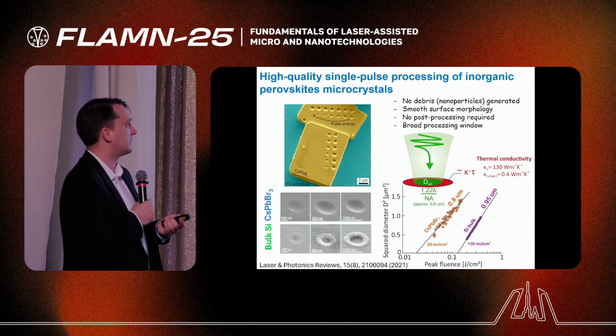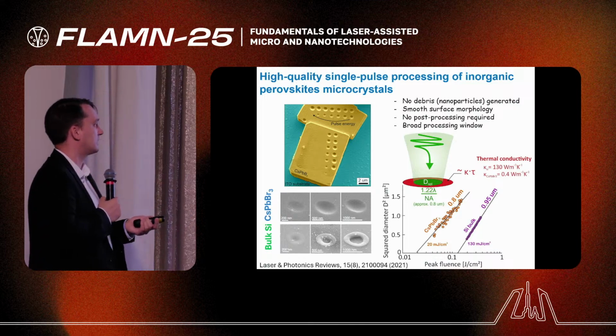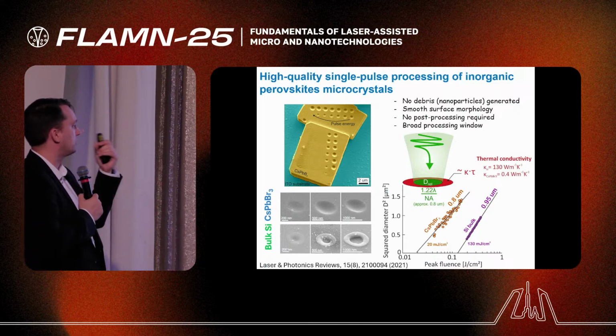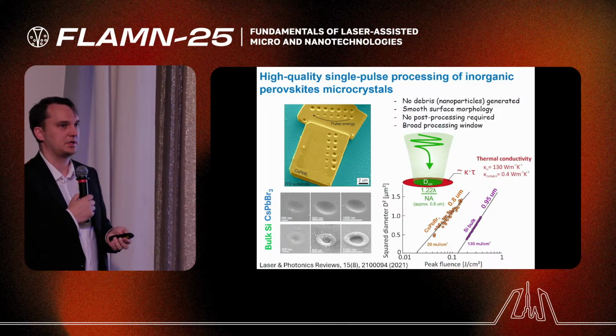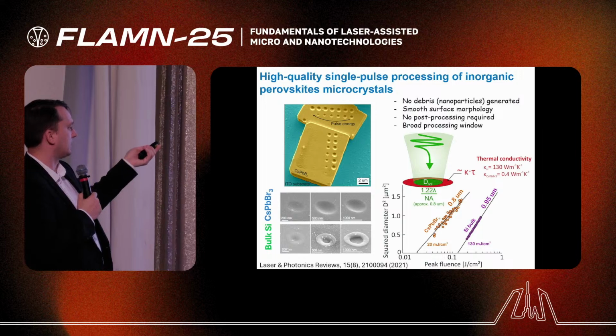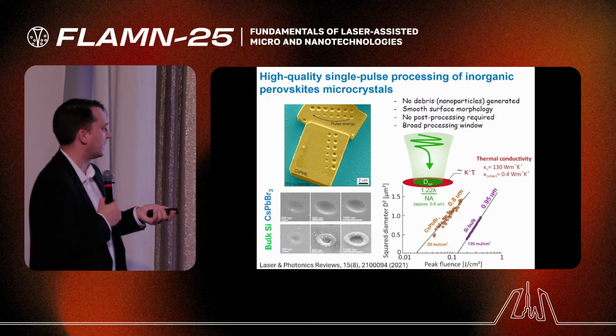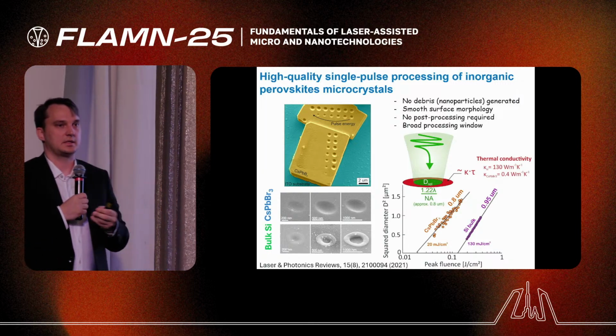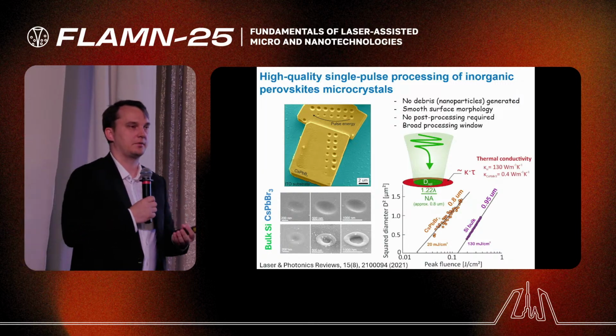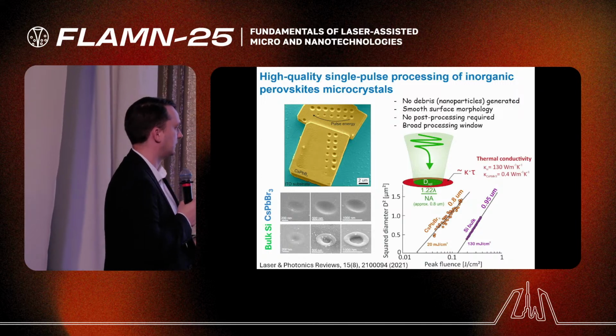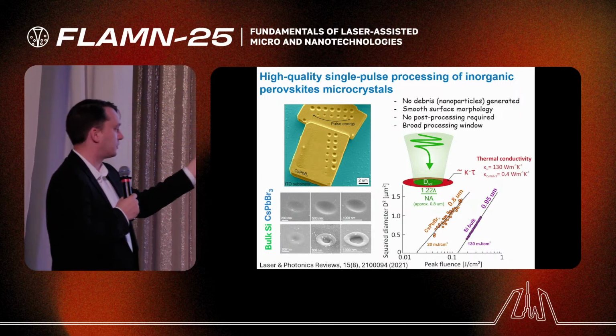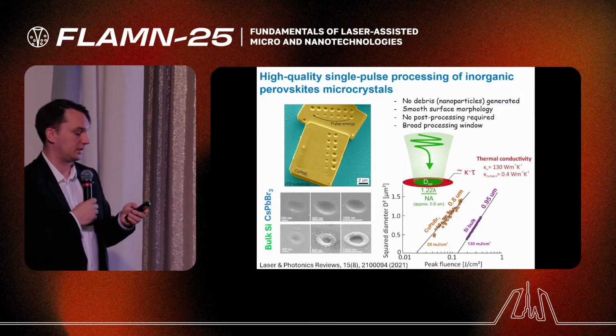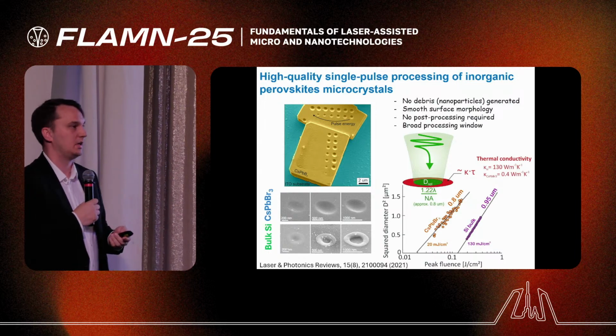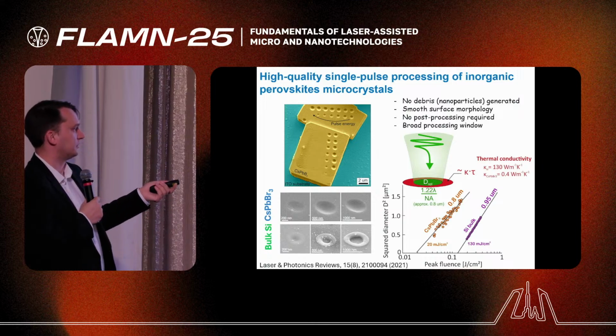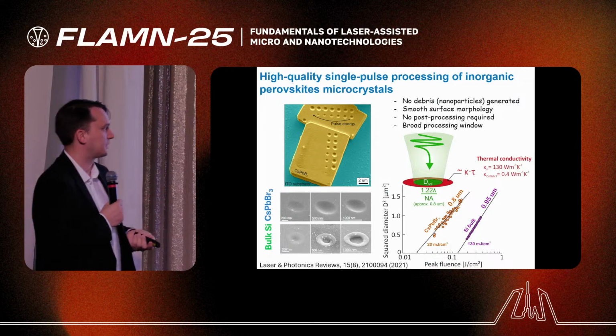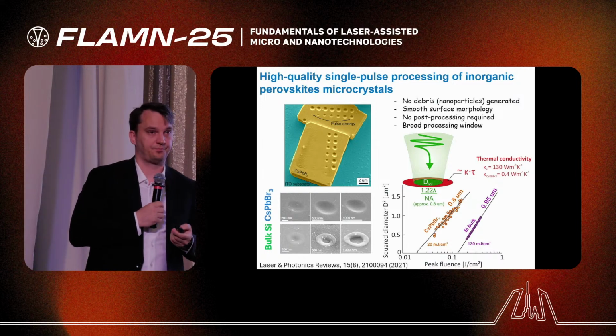And some first examples showed us good quality of perovskite laser ablation. You see, if we compare silicon and inorganic perovskite, cesium lead bromide, we see that at the same conditions we have different quality of the ablated region. So the same focusing conditions and the result is different. Here you see that for perovskites ablation is much more clean. And the heat affected zone also is much less for perovskite as compared with silicon from our measurements.